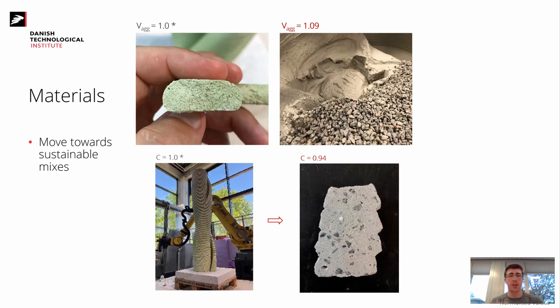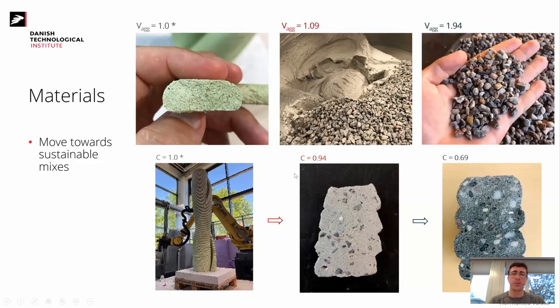Once we started our test with concrete, we could already reduce the cement content of that mix by 6 to 7%, and also change the cement type. But then lately we went all the way to reducing by 31% the amount of cement content. Of course, you're now replacing all your fine materials, including cement and sand, with large aggregates. Of course, using large aggregates imposes different challenges in terms of equipment wearing and the quality of the extrusion process itself. But this is a trend that I would like to bring to the audience, because in order to make 3D concrete printing more competitive to the construction market, there is a need to first make sustainable mixes that are not only sustainable, but much cheaper than the mortars being used at the moment.